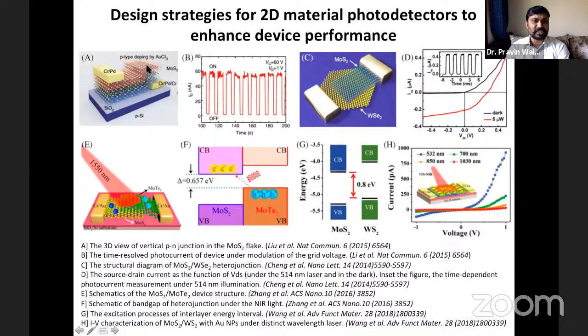But let me compare these first two devices. Here, this is the homogeneous PN junction, and this is the heterojunction, right? So what is the importance of having the PN junction versus the heterojunction is that the quantum efficiency of this device is quite low. It's almost 0.1 to 1%. But in this case, these people have observed quantum efficiency up to 12%, right? So the improvement in quantum efficiency comes just by changing the strategy, just by using two different 2D materials. And here, MoTe2 is absorbing most of the light spectrum, and therefore a wide spectrum range is covered in this kind of device as compared to the first two devices, right?